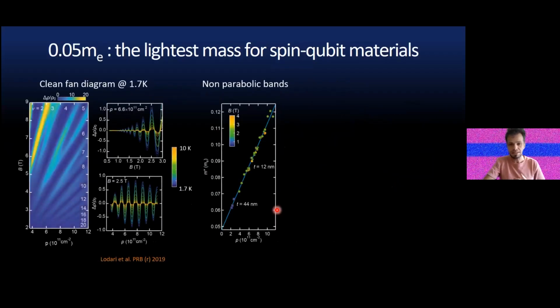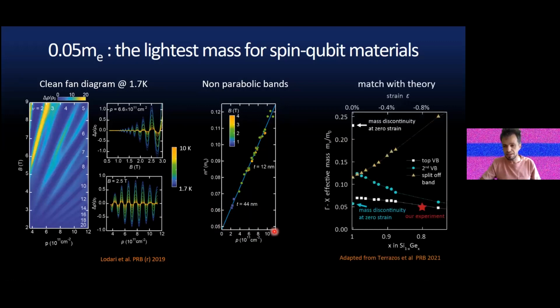The other real promise that we fulfilled was the one of the effective mass. So these high quality wafers enable a detailed magnetotransport characterization with a fan diagram, so tracking the Landau level energies as a function of density. And from here, by thermal activation, we can extract the mass as a function of density. And you see here that you have a dependence of the mass on the density due to the fact that the bands are actually non-parabolic at a finite Fermi wave vector. But if you extrapolate this to zero density, you get a mass of 0.05, which really matches the theoretical predictions.